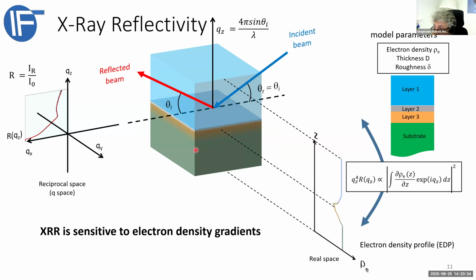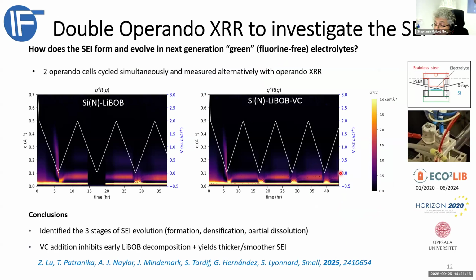So reflectivity is quite simple. You have a stacking of materials with different electronic density, and by changing this angle, you measure the reflected beam and you can measure this curve: intensity as a function of the angle, of the QZ direction. You can apply a model to fit the data in order to get the electron density profile. And from this density profile, you can deduce a lot of things. So the first example is to get rid of some fluor in the electrolyte for battery technologies.